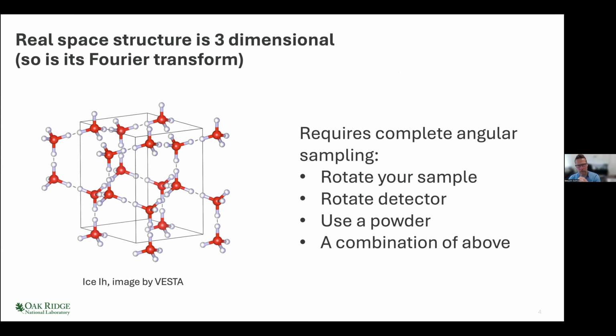So of course, the real space structure is a three-dimensional thing, and therefore so is its Fourier transform. So if we want to try and quantify that, we need to do some kind of angular sampling. And so typically that will involve either rotating your sample, rotating the detector, or doing both of those things, or you use a powder, which is a nice trick where you have many crystallites, they have a randomized orientation, and just by hitting all of them at once with one beam, you're sampling those orientational distributions and therefore getting your 3D information.